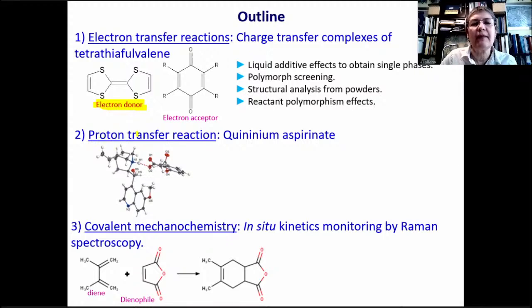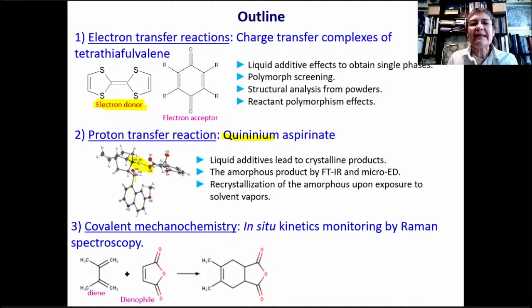So the second type of reaction to study is a proton-transfer reaction, the formation of a salt between quinine, the antimalarial, and aspirin. And we can see here a proton transfer from the aspirin molecule to the quinine molecule. And in this case, the liquid additives lead to crystalline products, but using no additive, just by neat grinding in a mortar and pestle or neat ball milling, an amorphous powder is obtained.